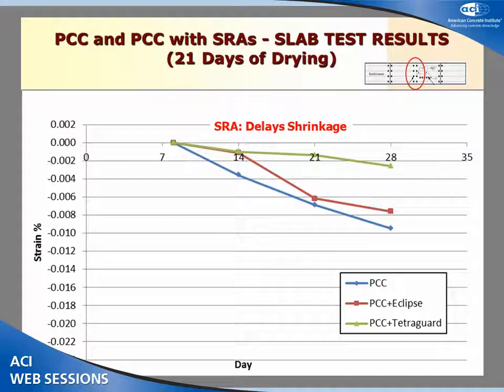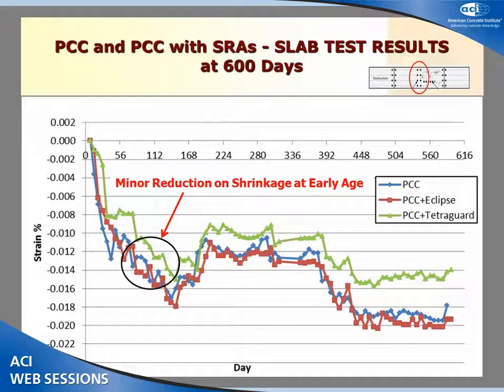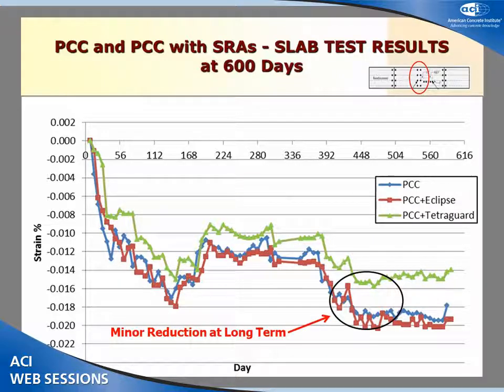This graph shows the Portland cement concrete and the shrinkage reducing admixtures we used, for 28 days, which is 21 days of drying. You can see the shrinkage reducing admixture delays the shrinkage in these first few weeks. And here are the slab results for 600 days, showing that there is a minor reduction in shrinkage at early age and almost none in the long term, for 600 days of results.